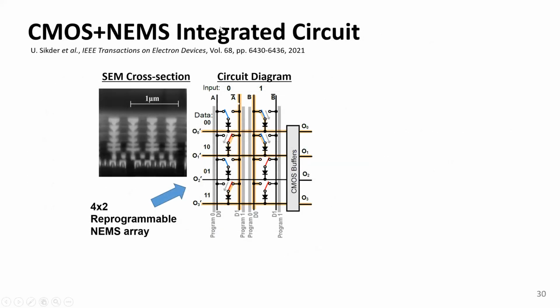Okay, so at Berkeley, we're exploring new hardware architectures for edge computing devices for which energy efficiency is a critical requirement. Shown here are experimental results for a hybrid CMOS. On the bottom, you can see these FinFETs and NEMS. These are patterned beams in the back end of line interconnect so that they can move back and forth. This is a circuit implemented using TSMC's standard 16 nanometer CMOS process. And this cross-sectional SEM shows the fabricated circuit on the left, and shown in the middle is a circuit diagram.